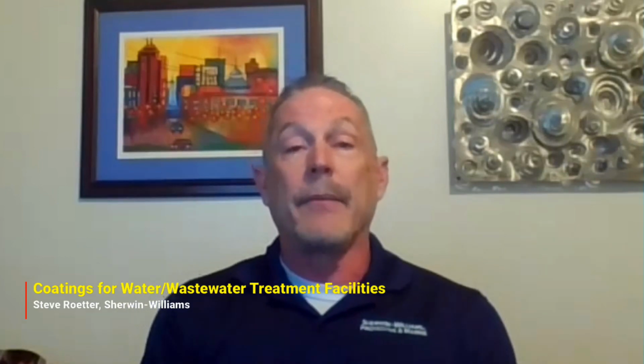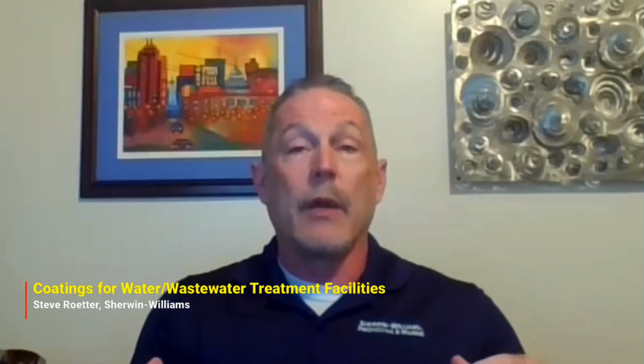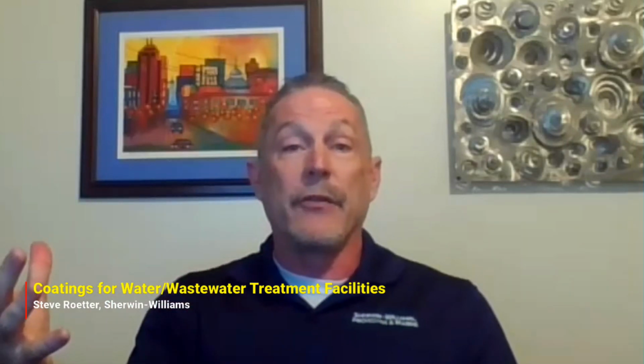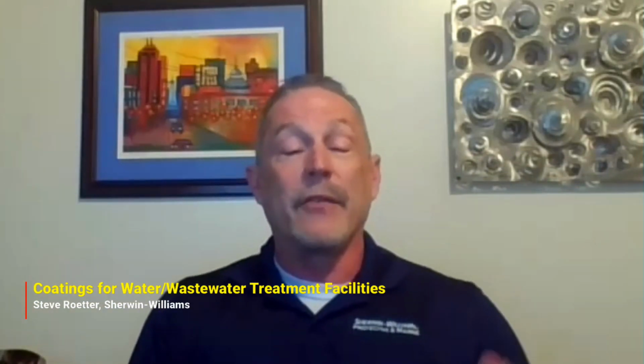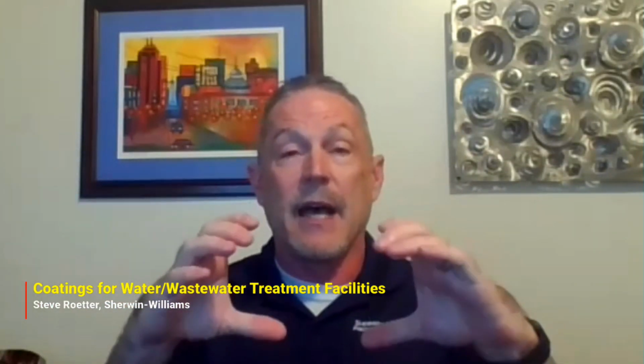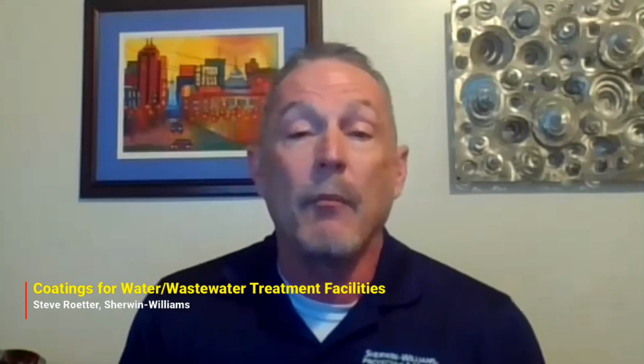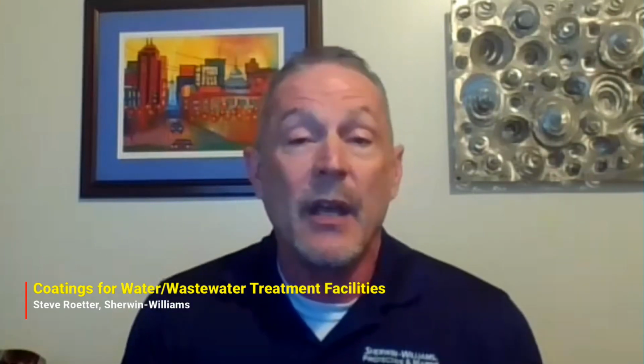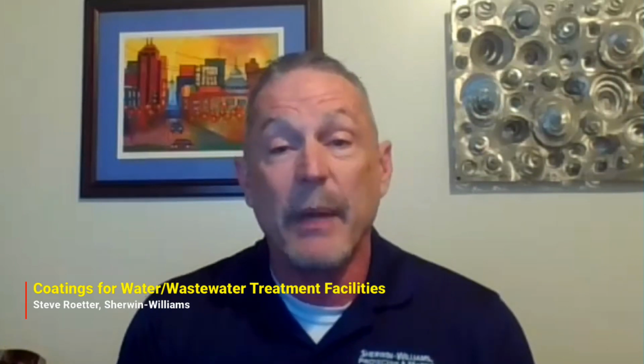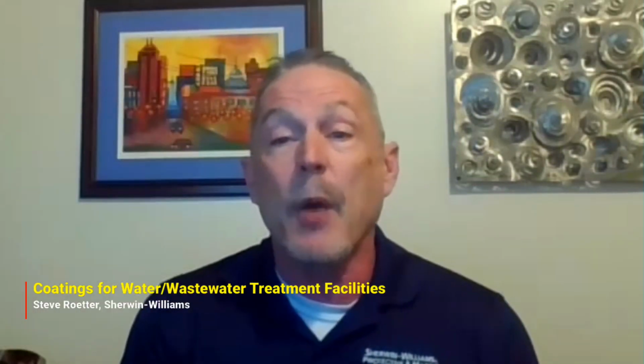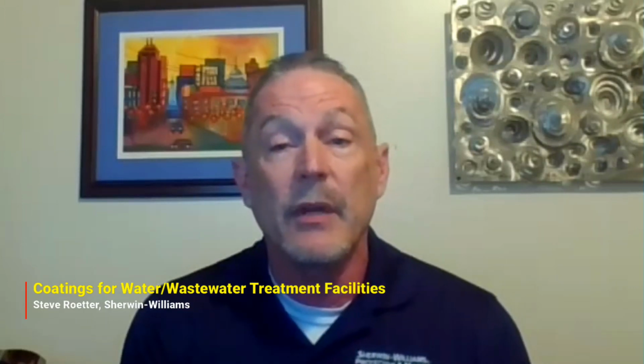But a third thing that's happened is air quality regulations and public relations. Now, because of these air quality regulations we've promulgated and public concerns regarding the odor from H2S in wastewater treatment plants, we've started to put covers over a lot of the facilities. And what these covers do is trap the H2S inside and allow it to build up to much higher concentrations and collect in the headspace. So, in general, prior to 1980, in the 70s, H2S levels you'd encounter in headspaces were generally 10 parts per million in most sewer systems.